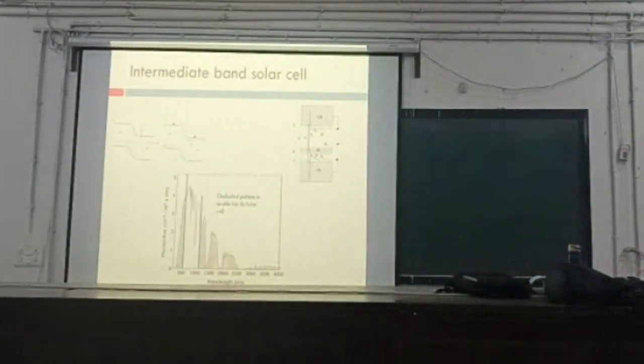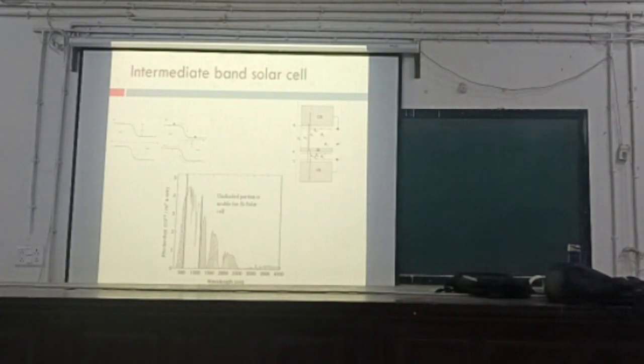That corresponds to 1100 nanometers. So if you have a photon whose wavelength is more than 1100 nanometers, that will not be able to create any electron-hole pair in silicon. The 95% solar cell market is of silicon material, right? Whose band gap is 1.1 electron volt.